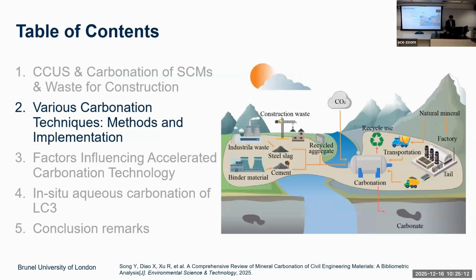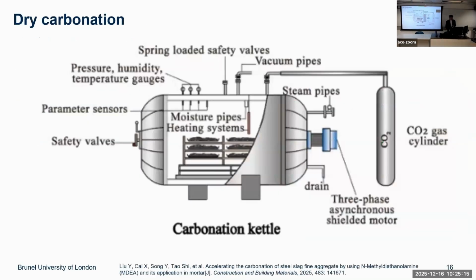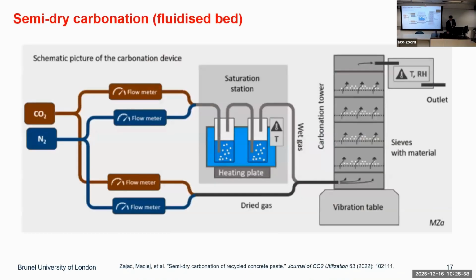Now we just want to summarize the current carbonation techniques. One is dry carbonation. This one is taken from a paper from Zhejiang University of Technology. Ian was my visiting PhD student, and they developed this carbonation chamber, co-developed with tire manufacturers. This is a typical dry carbonation for the products. You need higher surface areas and more porous particles, and you need to control the gas and the flow rate. The good thing about dry carbonation is that it's easy to proceed, but it needs special equipment because you need to control the temperature.